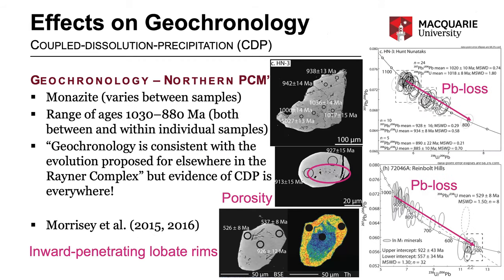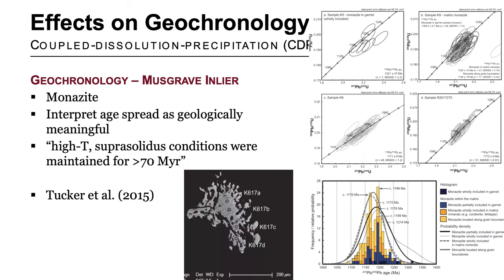I'll move quickly through the next few examples, as the story is pretty much the same. A spread of near-concordant ages is interpreted as long-lived metamorphism that lasted for tens to a few hundred million years. Note in this example from East Antarctica, the porosity in some of the monazite grains and those inward-penetrating lobate rims shown in the chemical map that are suggestive of coupled dissolution-precipitation. In the Musgrave inlier, long-lived metamorphism lasting more than 70 million years. Again, note the porous monazite in the picture.